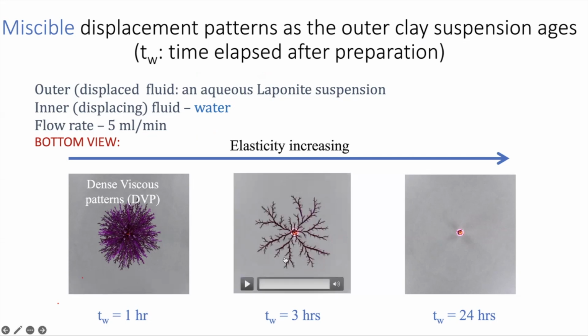One word about side branching. The reason why that happens is that the fluid outside, the clay, is shear thinning. So the water that is propagating into the clay at rather high velocities shear thins the clay at the propagation front, and the combined effect of that shear thinning results in the finger propagating faster. But remember, the driving pressures on the water are also very high. So that tends to make the branch.